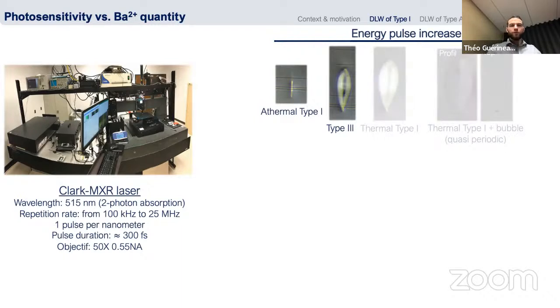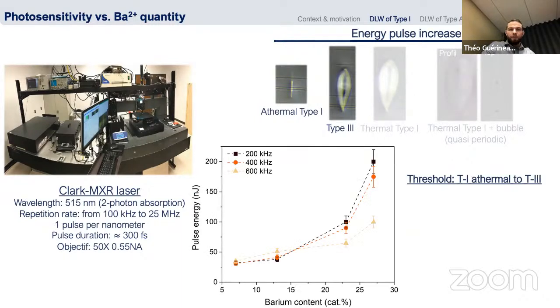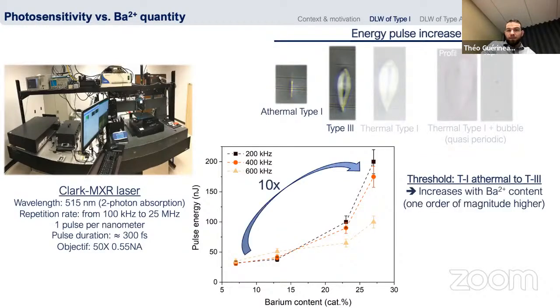So first I will focus on the threshold between the athermal type 1 and the type 3. This graph represents the evolution of this threshold considering the pulse energy and the barium content for 3 different repetition rates. First, in the 3 cases, you see that when we increase the barium content, we gain 1 order of magnitude higher for this threshold.